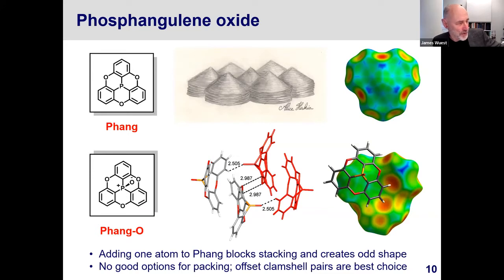Now, one of the things that can be done by crystal engineers to explore molecular organization and why a particular organization is favored and why certain organization is disfavored is to take a structural motif that is encountered and create some kind of obstacle that prevents that motif from being formed. So phosphangulene has this characteristic ability to form stacks. But if you convert it into phosphangulene oxide, or the corresponding phosphangulene sulfide or selenide, you block that stacking. And then the question becomes, well, what does that do? What alternative structures are available to a compound that now has a much different shape, an odd shape that's going to be hard to pack?